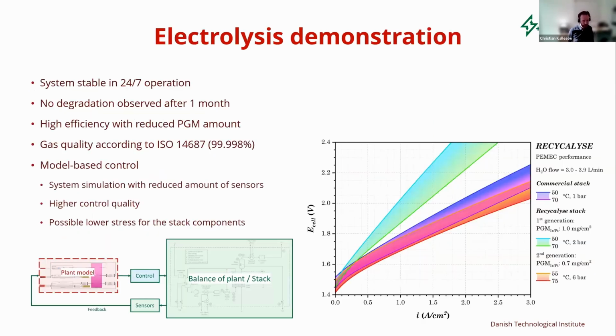Just to go briefly through it, the stack showed stable operation. If you look at the graph, don't focus so much on the green one. That was a first try, or only halfway through the project. But if you compare the purple lines and then the orange lines, that is a commercial stack with a higher amount of PGMs, and then our stack, which just showed that we actually made both a material, a MEA structure, and a stack that performs better than the commercial alternatives with a lower amount of PGMs, with a high gas quality. And all in all, we optimized this system, which was based on model-based control, so we can really reduce the amount of sensors. I will not go so much into depth into this part of the project.